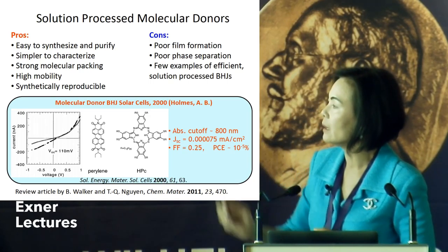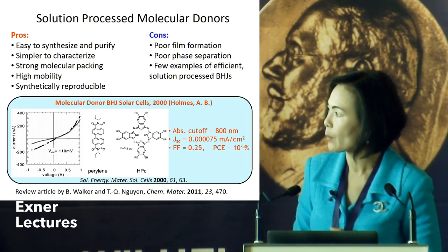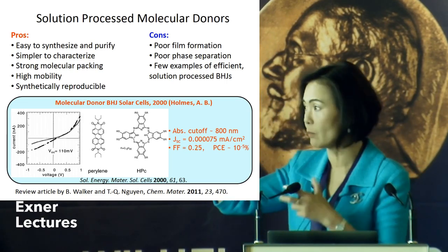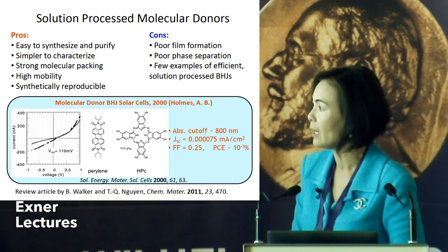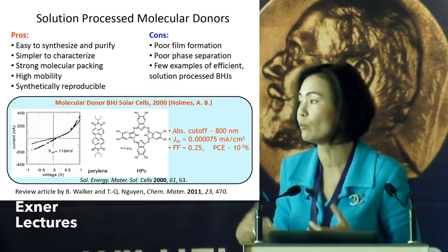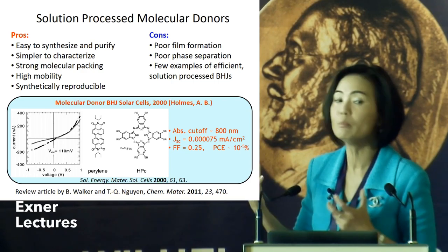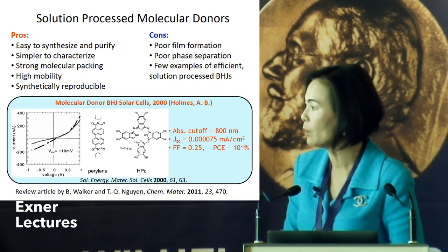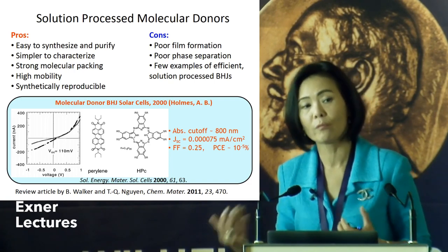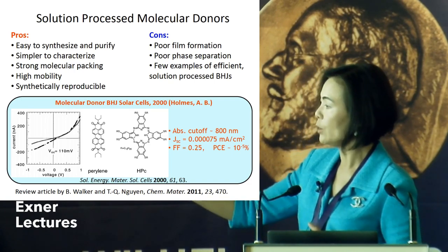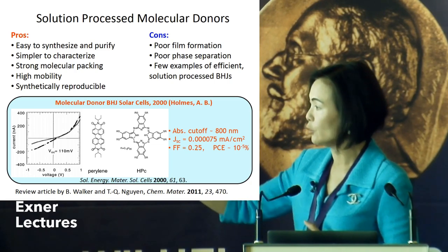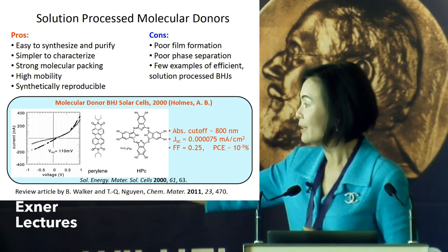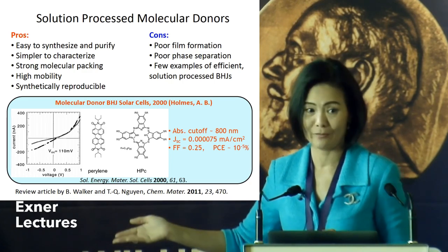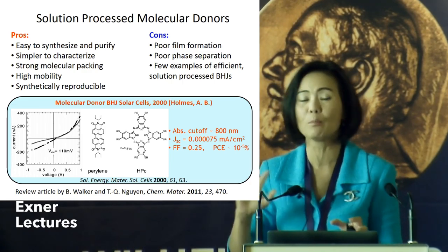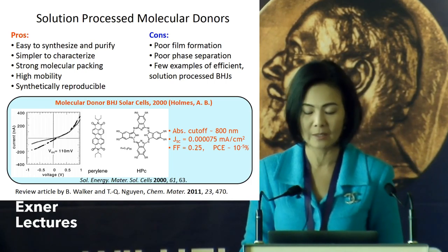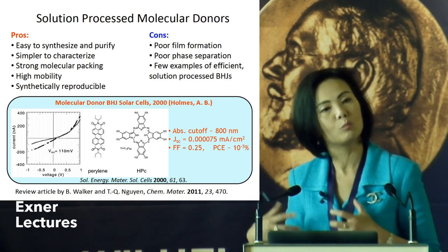And so the pro of this approach is that it's easy to synthesize and purify. You just run a column, you purify a few times, and it's straightforward to functionalize to make the molecule. And then you have good molecular packing, so you have better charge mobility. But we were not the first ones to use the approach. We looked, and there was a paper in 2000 using the small molecule approach. But the efficiency was 10 to the minus 5. It's extremely low, and that's why people were not interested in using this approach. Okay? But again, we did give it a try.